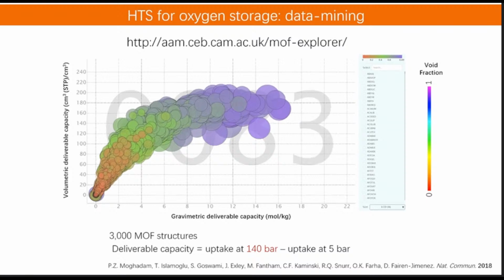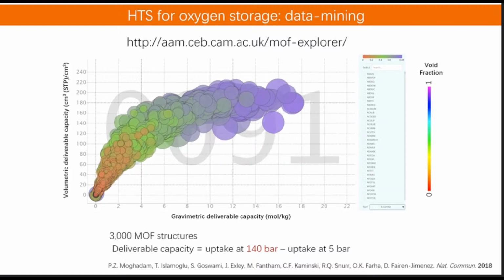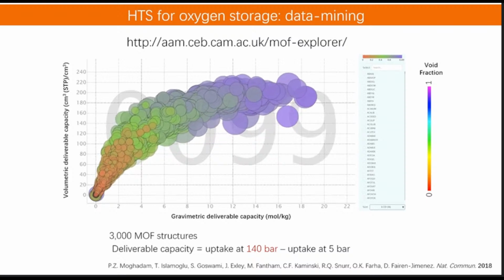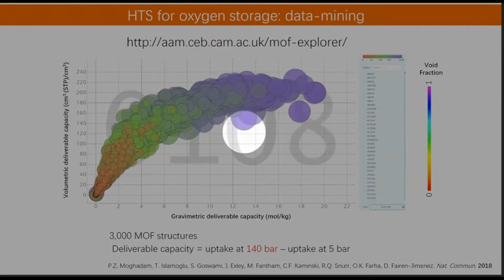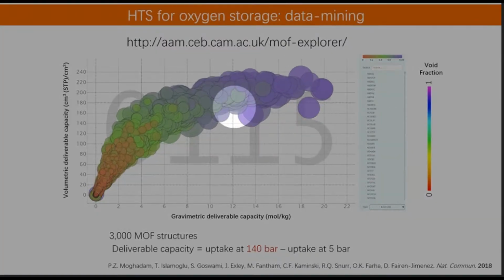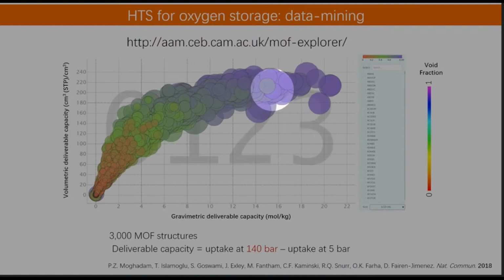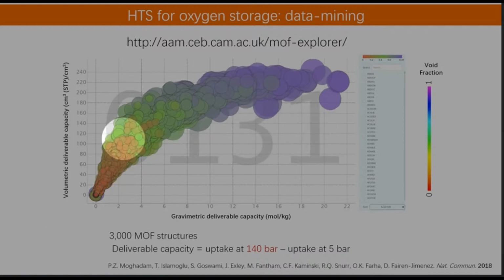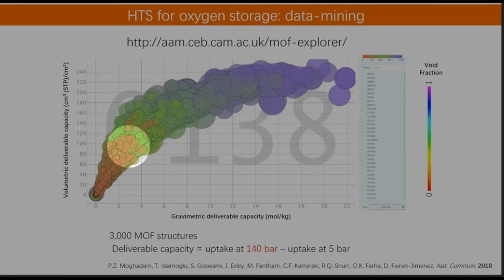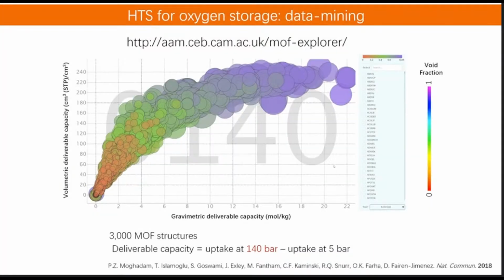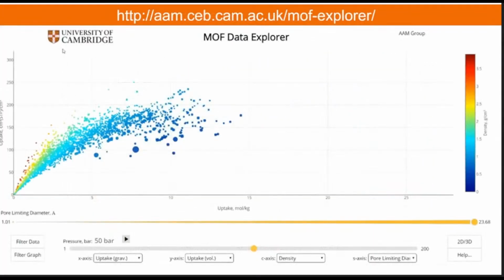And this is important because this will allow us to really understand different ideas that we have with these materials. For example, the fact that these materials, the purple one, will continue growing when we increase the pressure, whereas these orange materials that we had here were stuck at much, much lower adsorption capacities. This is how the Explorer looks in reality, okay?